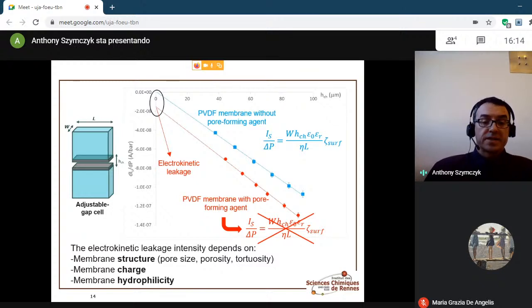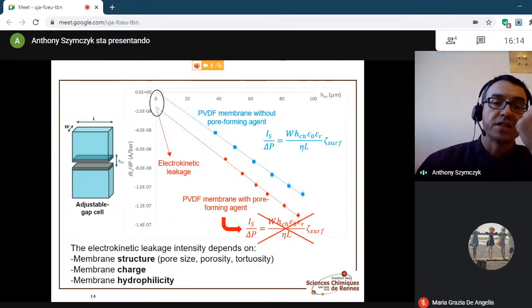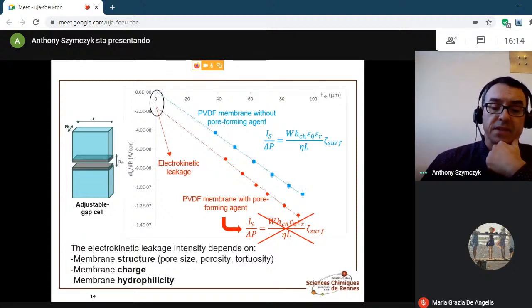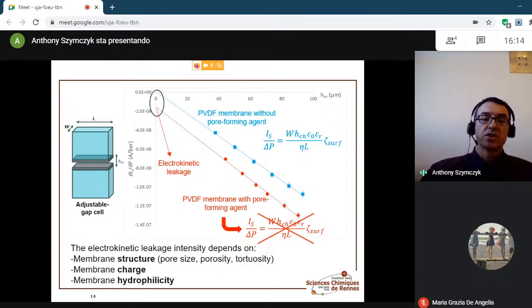To do this, a series of streaming current measurements are carried out by varying the distance between the two membrane samples. For each distance, the streaming current coefficient is extracted, and it is plotted as a function of the distance between the membrane samples. As can be seen here for a PVDF membrane, synthesized by phase inversion, but without the addition of a pore-forming agent. This is the result shown by the blue symbols. The variation of the streaming current coefficient with the distance between the samples is linear, in agreement with the electrokinetic theory, and the extrapolation of the experimental data to a zero distance passes through the origin.